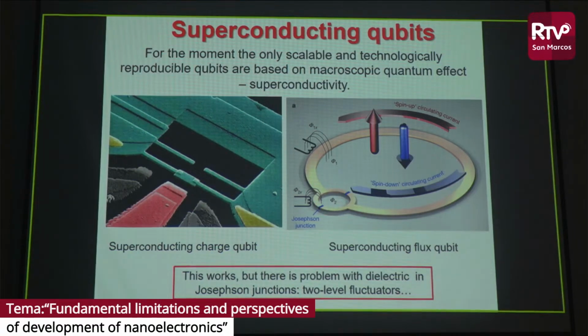There are also some hybrids, like for example fluxonium, but all of them can contain tunnel junctions. For example, here it is this region, and here it is this region where there are two Josephson junctions. And it appears that the decoherence time, which should be as long as possible to preserve information, is strongly dependent on the quality of these insulating barriers. And in all of them, there exist so-called two-level fluctuations which kill the coherent state of a qubit. So there is a claim that if one is capable of making a qubit without a tunnel barrier, using only metals, it should have some advantage.